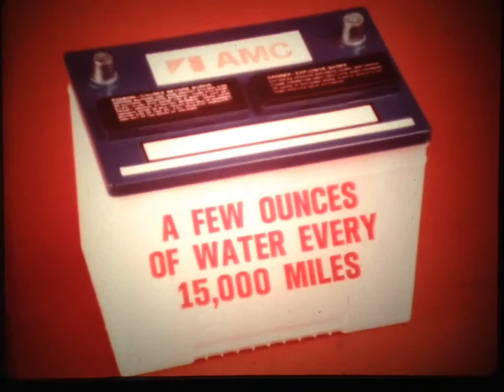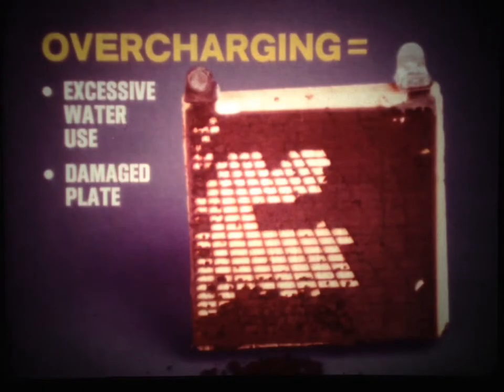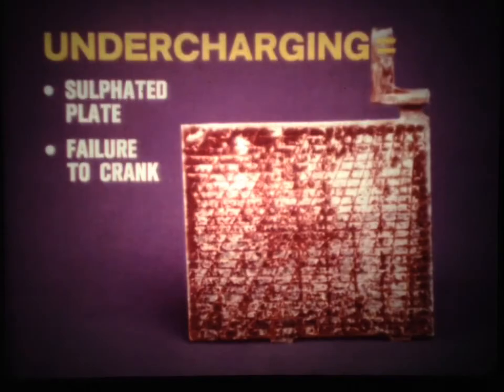With normal driving and temperatures, the battery should use only a few ounces of water every 15,000 miles. If the battery seems to use an excessive amount of water, this may indicate that the battery is being overcharged. Such overcharging washes active material from the plates, and the heat involved can warp the plates. Testing can reveal damaged cells.